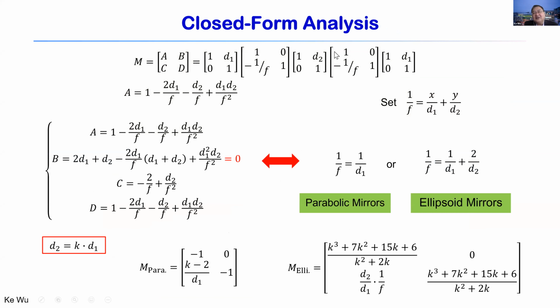From this formula, we can get to this ABCD total matrix, and to develop this so-called frequency independent optic path, you need to set B equal to 0. The B is this one. B equal to 0 means that you create the frequency independent path. And in this case, you have two scenarios here. For parabolic mirrors, the focal distance should be equal to D1. Or in the ellipsoidal mirror systems, the F is associated with D1 and D2 values.